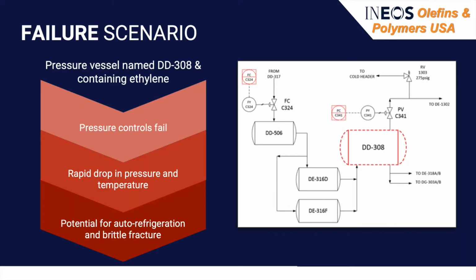On the right, you can see the initial schematic provided by INEOS to the team. The pressure vessel outlined in red, DD308, is the pressure vessel experiencing brittle fracture conditions. This is a result of pressure control failures, which lead to a rapid drop in pressure. This drop in pressure causes the liquid ethylene to evaporate, drawing heat away from the pressure vessel, thus resulting in a rapid decrease in temperature. This process is known as auto-refrigeration, which can eventually lead to brittle fracture.